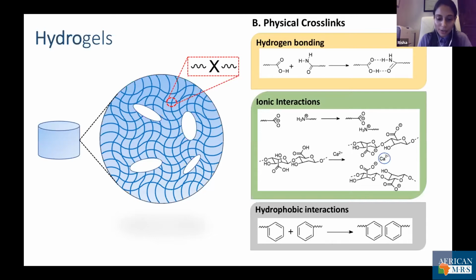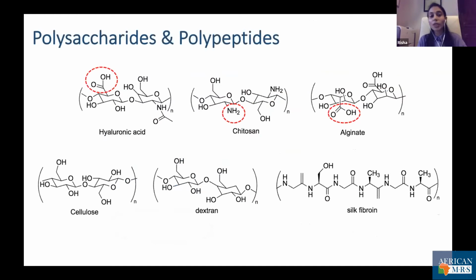Now, to this effect, we have a wide variety of polysaccharides and polypeptides, which have been used to synthesize these hydrogels. As for example, hyaluronic acid, chitosan, alginate. They provide functional groups such as carboxyl groups, amine groups, for cross-linking. Or we have cellulose, dextran, which are naturally available. They contain a large amount of hydroxyl groups, which can be modified to allow cross-linking. Or silk fibroin, which is a polypeptide with self-assembling properties.